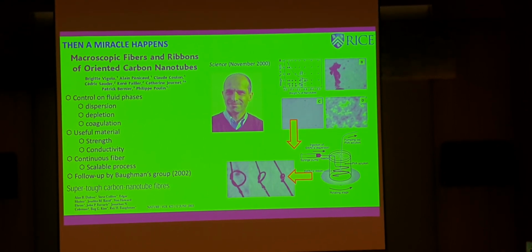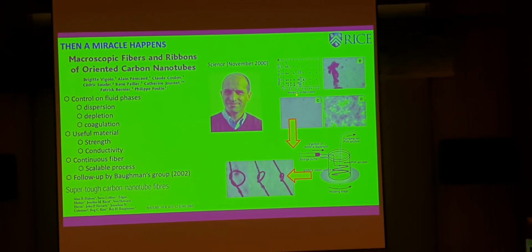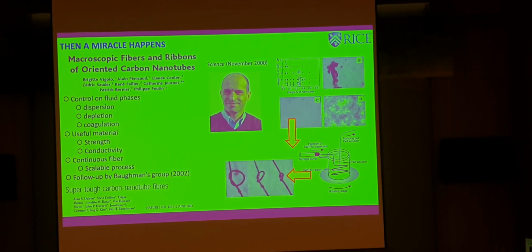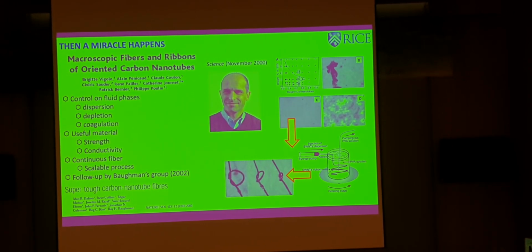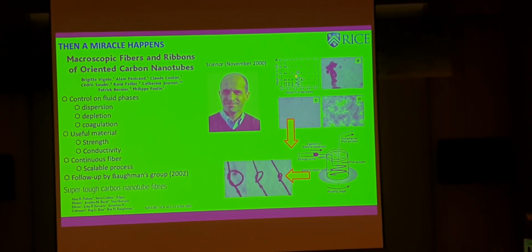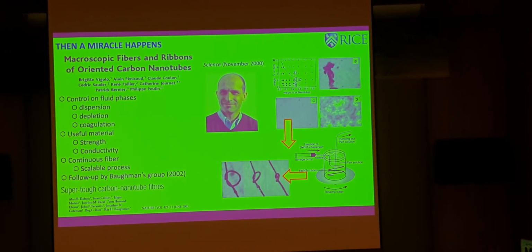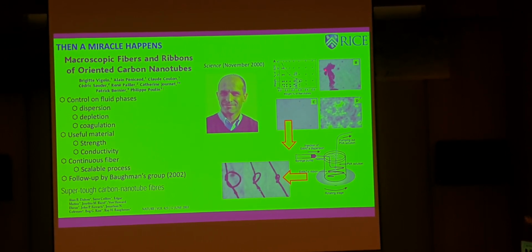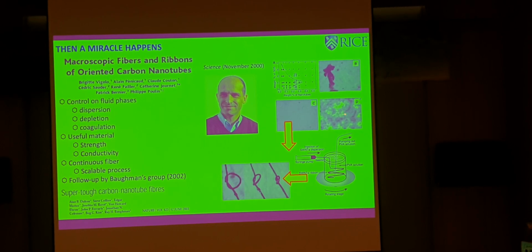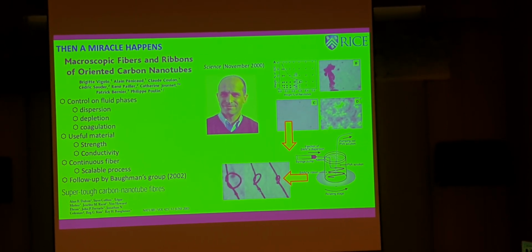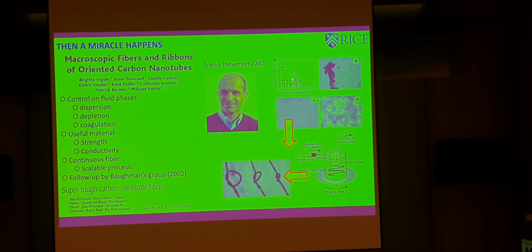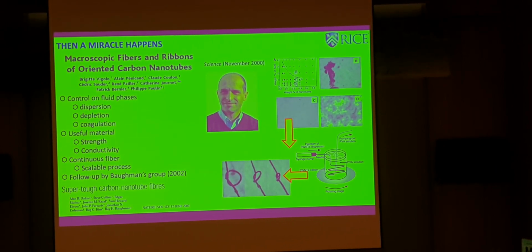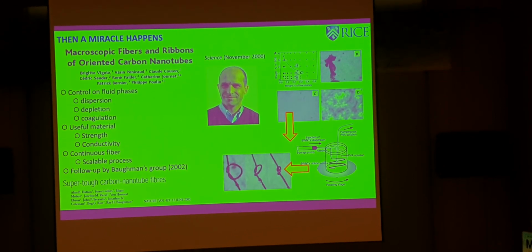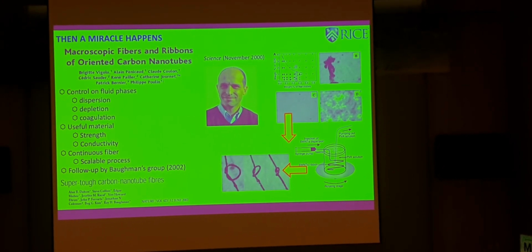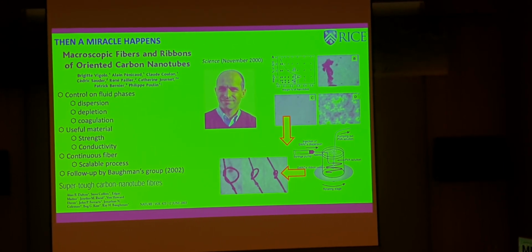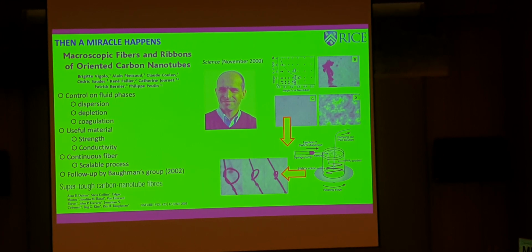What was very interesting about this article is that there was a lot of science. It wasn't just shake and bake. Philippe had really understood how to control carbon nanotube dispersions by using surfactants, and had shown that if you have not enough surfactant, then you end up with undispersed material, which is this type of morphology. If you have too much surfactant, you have depletion, and this was all explained yesterday in one of the talks. But if you have just the right amount, you can get a high enough concentration that you can make fibers. And it looked like a scalable process, right? You load up a syringe and you go. So you could make this gigantic syringe or a battery of syringes, and you never had to stop. So that was very exciting.